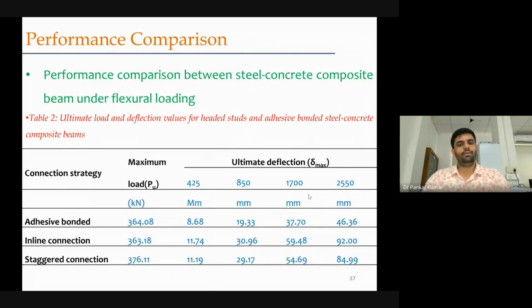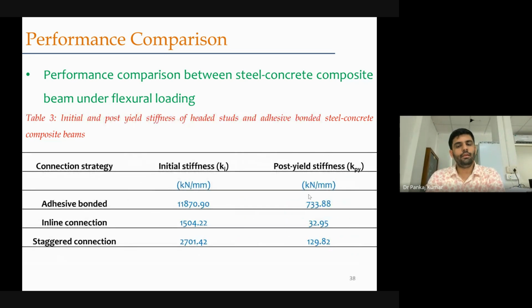If we look at all 3 beams, the ultimate capacities were almost the same. In the staggered pattern the capacity was a little bit higher, but for the inline and adhesive it was almost the same. But when it is about the deformation, we got a significant change, which we can see here also.